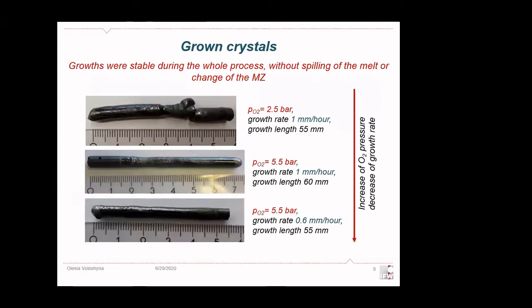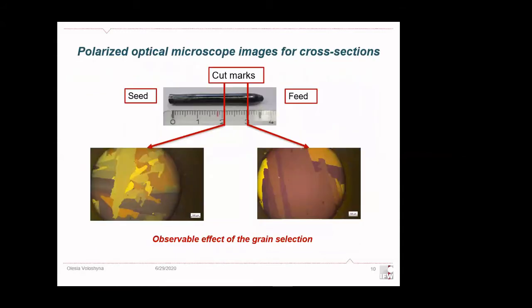So increasing the pressure in the growth chamber can be a tool to prevent the formation of bubbles in the melting zone. And as you can see from the comparison, with increasing oxygen pressure in the growth chamber and decreasing growth rate, we obtain crystals of high quality with a sufficiently big crystalline part of the single crystal.